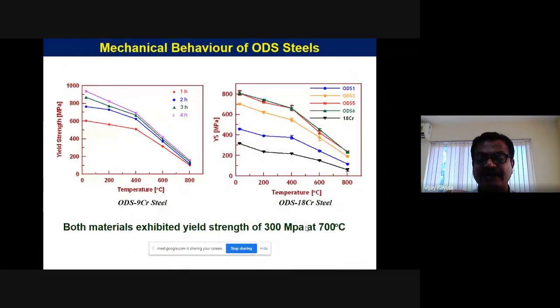And coming to the properties, we can see the yield strength at different temperatures. You can see that for our 9 chrome sample, we are able to see around 300 MPa. Of course, any material loses strength when you test at higher temperatures. And if you look at around 700 degrees, which is the operating temperature for the fast breeder reactor or the steam turbine, they're around 300 MPa. So the strength the material needs is only 100 MPa. But both 9 chrome and 18 chrome gave around 300 MPa strength at 700 degrees centigrade.